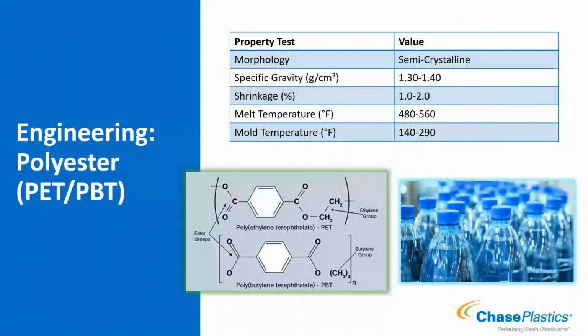And then we have, I believe the last engineering product we're going to cover, polyesters - PET and PBTs. We'll cover them as a two-part family, if you will. Both tend to be semicrystalline, though there is an amorphous version of PET we'll talk about briefly. Specific gravity is between 1.3 to 1.4, depending on which one it is. Your shrinkage is between 1 and 2%, again depending which one you're looking at, but since they are semicrystalline, you do see a larger value for shrinkage. Your temperatures are in the 500-ish range, and your mold temperatures are in the 1 to 200-ish range.